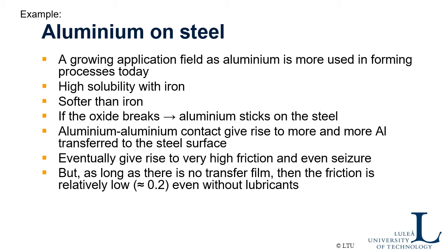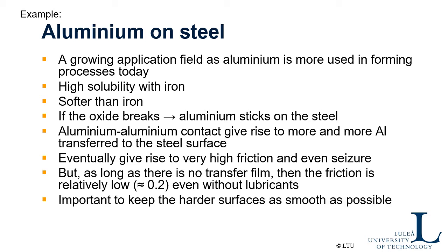But as long as there is no transfer film, as long as the oxide is remaining there, you maintain a friction coefficient that is relatively low, say 0.2. So this is an adhesive friction problem, you can say.